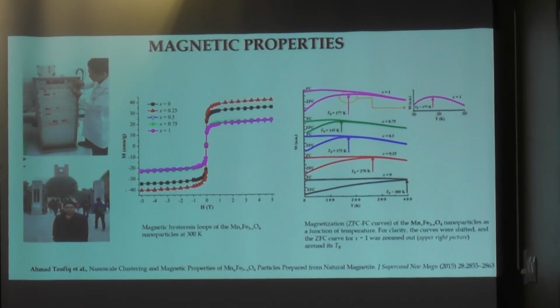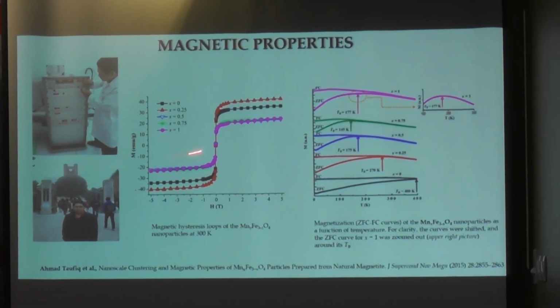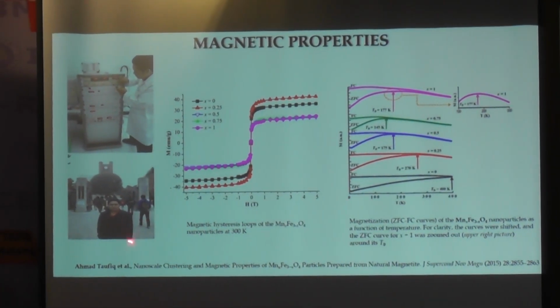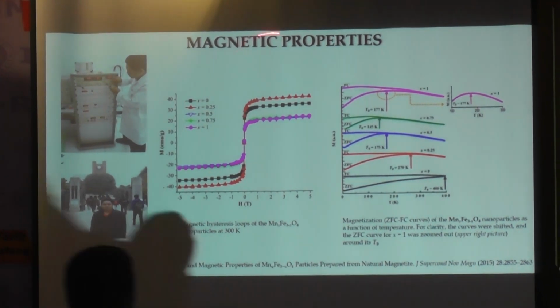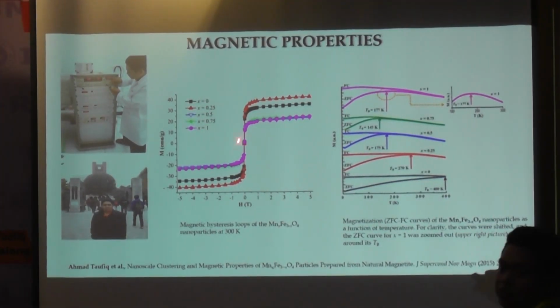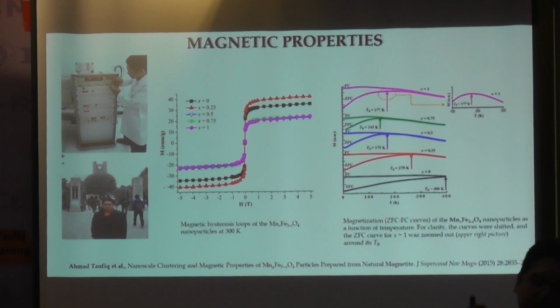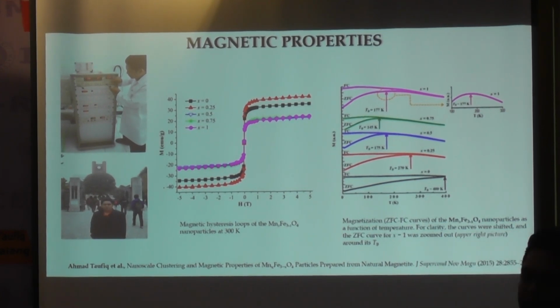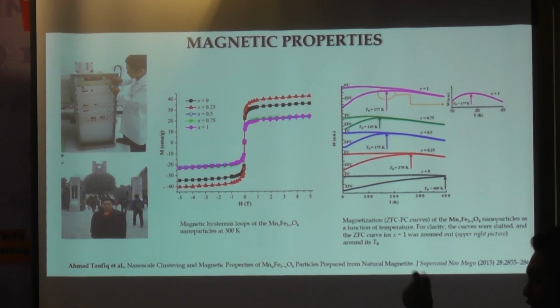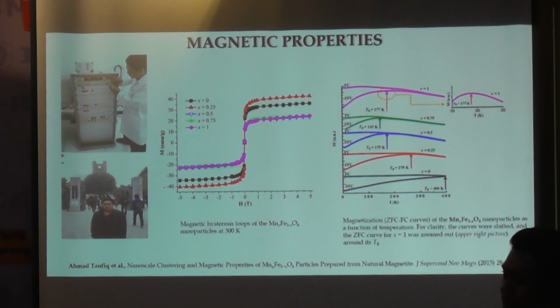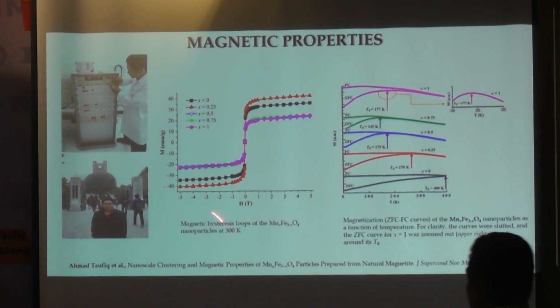And magnetic properties. We measured it at the University of Tokyo. From this data, we can see in here there is no coercivity. This gives us the guarantee that this is superparamagnetic. The particle size alone does not fully guarantee that this is superparamagnetic. From this data, this is superparamagnetic, no hysteresis. From ferromagnetic change to superparamagnetic.